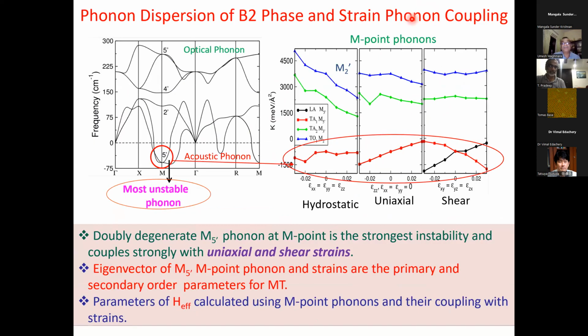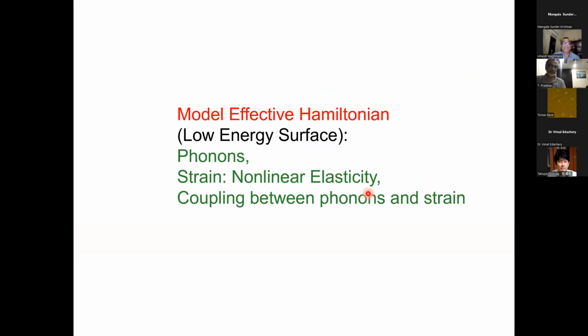So this is an example of a phase transition where many phonons are involved, although there was only one specific unstable phonon. And these phonons are very sensitive to the strain. If you apply hydrostatic strain or uniaxial strain or shear strain, the frequencies change rapidly, and that's the coupling between strain and phonons which are relevant to this phase transition. So based on this, we develop a model effective Hamiltonian. Again, I will skip all the mathematical details, but basically this model Hamiltonian captures the lattice anharmonicity of phonons, of strain, basically nonlinear elasticity, and the coupling between phonons and strain, which is also nonlinear coupling.